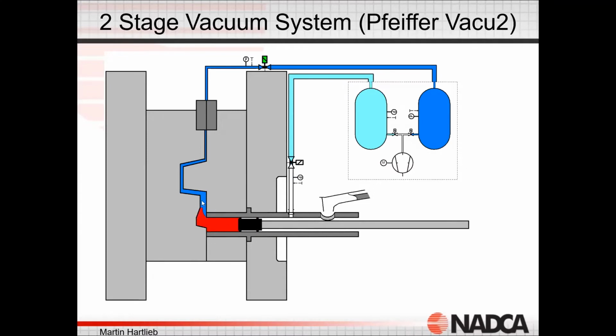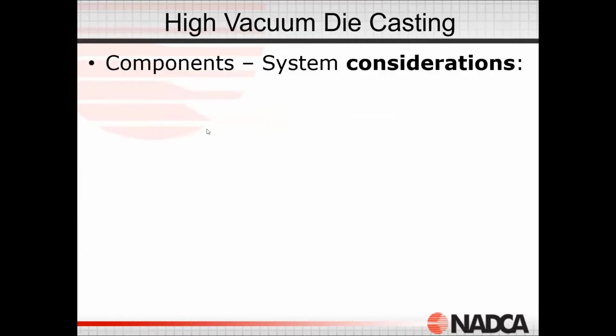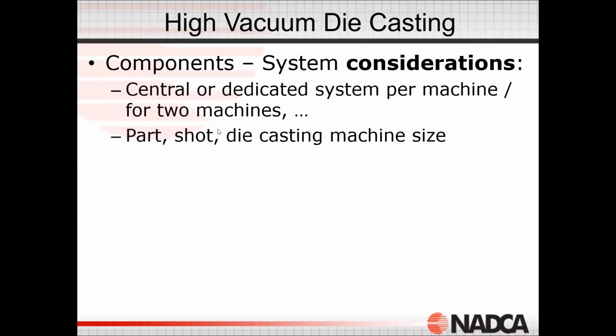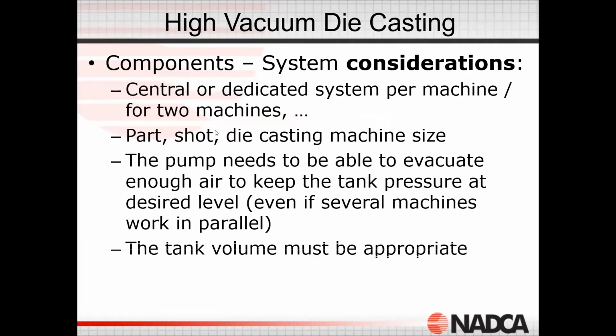The metal is now entering the cavity shape, fills the entire cavity shape, and then the vacuum system turns off as it reaches the top vacuum point. And there's several ways that's achieved. With that vacuum off, the mold is now filled, the casting solidifies, and we pull the casting out of the mold, and then the process repeats. So that shot fill time, once again, is between 49 milliseconds, 0.049 seconds, to about 0.09 seconds or 90 milliseconds. So very rapid filling.